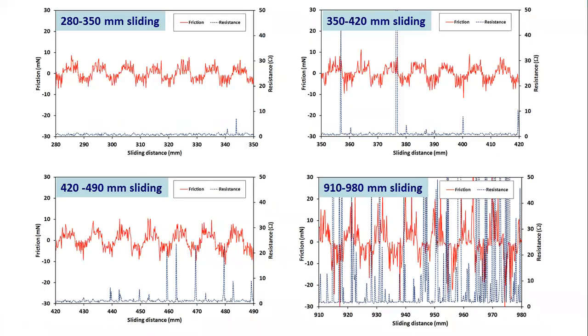So if we take a typical test, these are just 4 snapshots at different sliding distances. The first one is starting at 280 millimeters of sliding, because nothing happens before that point. And we can see the friction stays low, the electrical contact resistance stays low right up until we get these small isolated events occurring just after 340 millimeters sliding. If we run that test on, we can see again these periodic small events. Run it on a bit more again, we can see these relatively small isolated failure events. And we run the test on a lot further, and we can see progressively more of the test sample is failing.